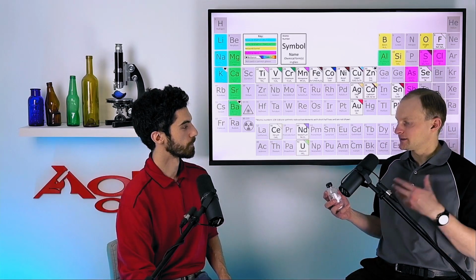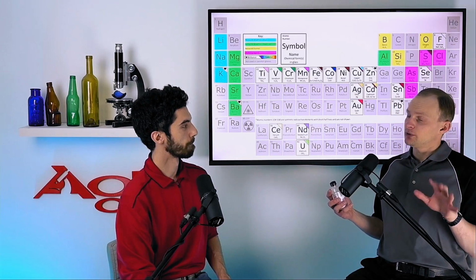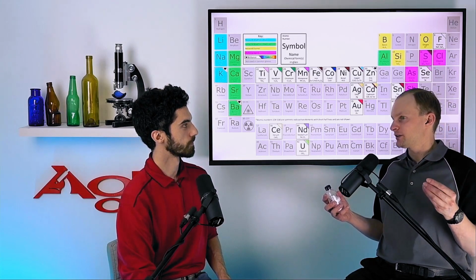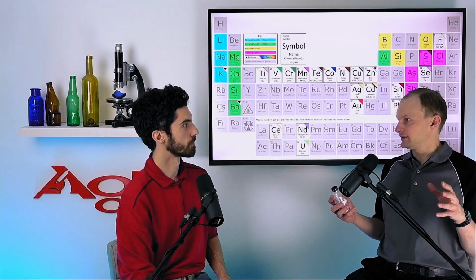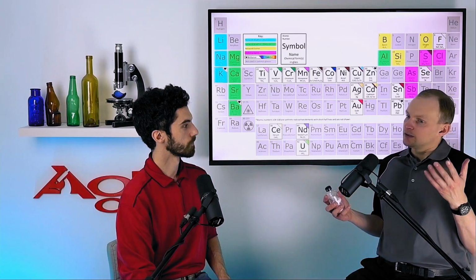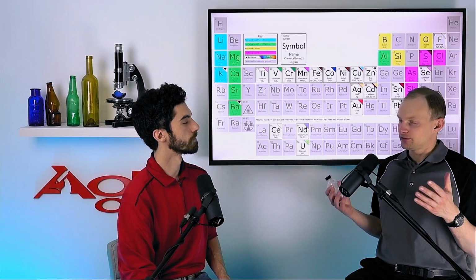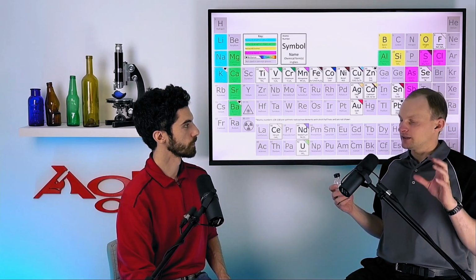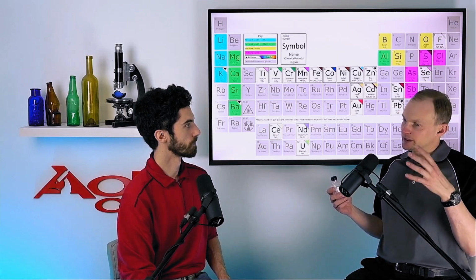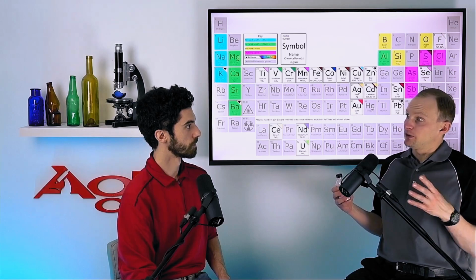When we are making glass, I mentioned the iron impurities that can be present. Well, that iron impurity is going to impart either a greenish color or a little bit of a yellowish color, depending on the oxidation state. We don't want that color to be there if we're making so-called flint glass, which is just a synonym for clear glass. If we're making that clear glass, we typically want to get rid of as much color as we can, but there's really no way to take that iron out once it's in there.